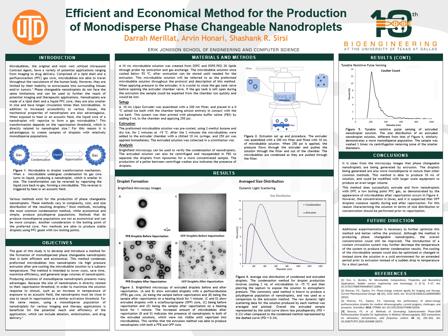When it comes to the monodispersity of the solution, you can look at the next two charts on here. Figure 4 specifically includes a comparison to a condensation method, which is known to have a polydisperse distribution. You can see by looking at the curves, the extrusion curve has less of a range, and so it is more monodisperse.